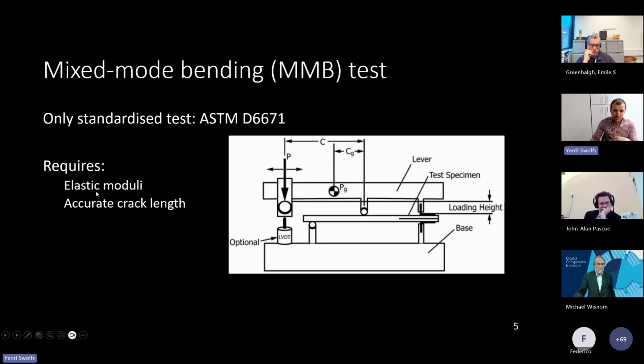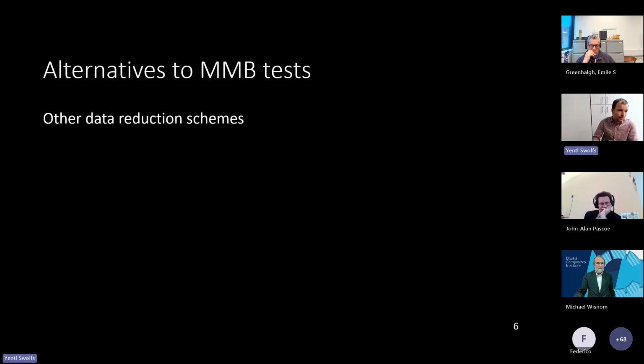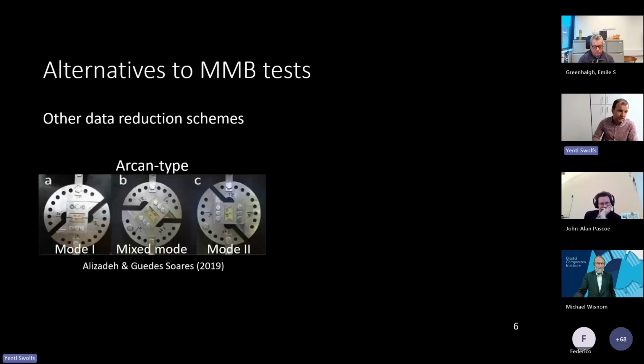The data reduction methodology does require the elastic moduli and also an accurate crack length determination. And this works reasonably well when it's mode 1 dominated, but the more mode 2 you get, the more difficult that crack length determination tends to be. So there have been other alternatives developed, a lot of other data reduction schemes beyond what is mentioned in the standard. There are also other actual tests like the Arcan-type tests, where depending on how you put the specimen or which angle you mount it in, you get either pure mode 1 on the left, pure mode 2 on the right, or mixed mode in the middle image.